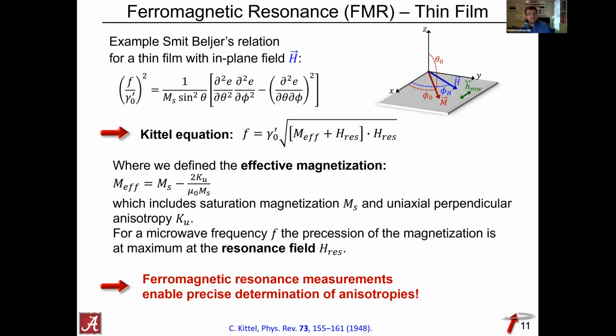which essentially gives you an analytic relationship between the driving frequency of your microwave field and the magnetic field at which the resonance then occurs. So the way to look at this is, if you drive the system at a given frequency, you can now tune the field to meet that resonance condition.